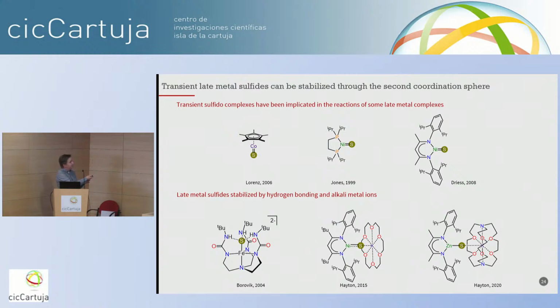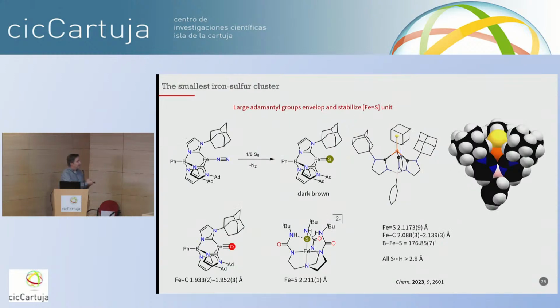Sulfur, of course, is well known to form a lot of bonds, to catenate, for example. But these sulfides have been proposed as intermediates in different reactions. And the only examples of stabilization are either through hydrogen bonding, as Andy Borovik showed, or Trevor Hayton has shown using alkali metals to cap the sulfide, so basically to quench lone pair character at the sulfide. So we thought maybe we could do the same thing. We have this very large adamantyl group. Maybe we can stabilize the sulfide. And this again worked first time.